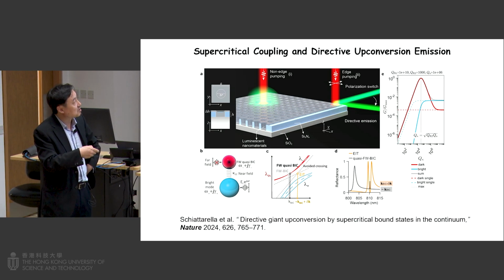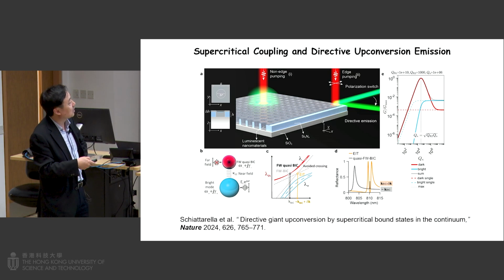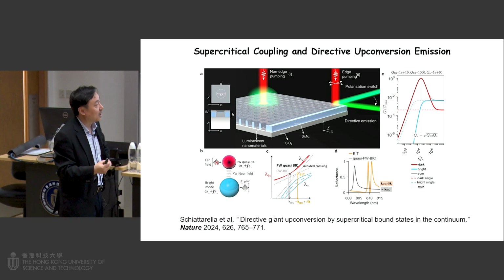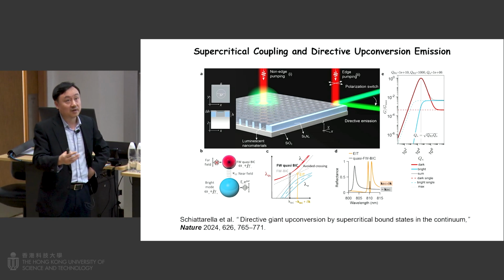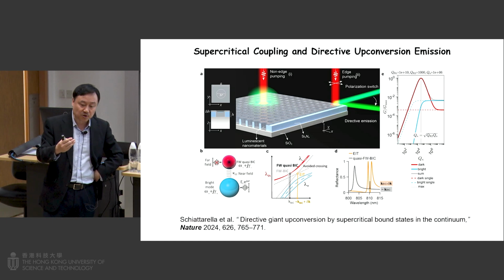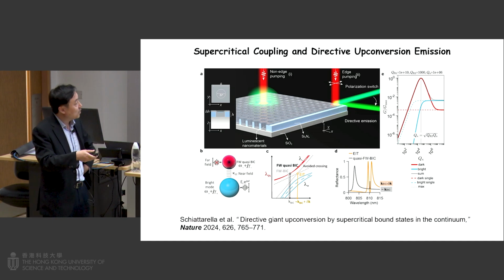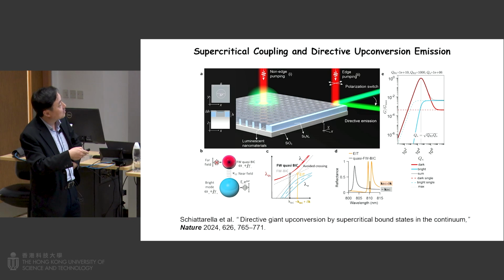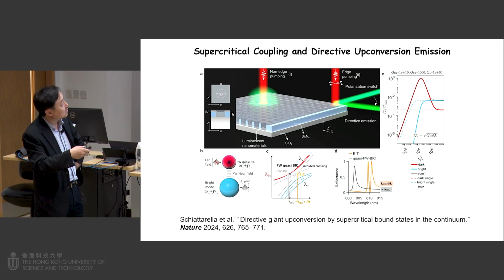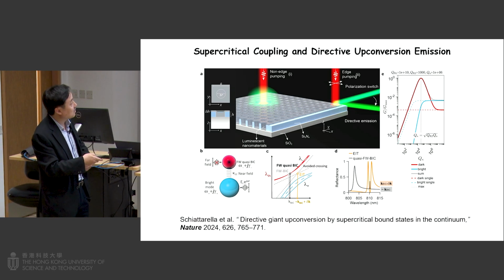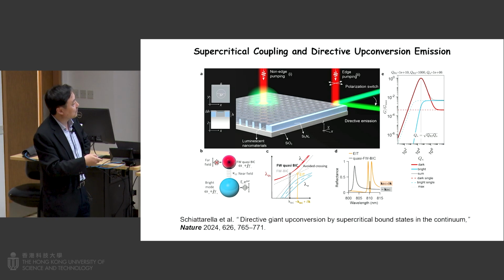of this metasurface. That's the most important discovery, using what we call the BIC structure, bound states in the continuum. The BIC structure is not a very new research area, but no one has actually reported this edge-enhanced direction control. We've shown that using a combination of the metasurface, dielectric materials, and upconversion materials, we can achieve very, very interesting optical phenomena.